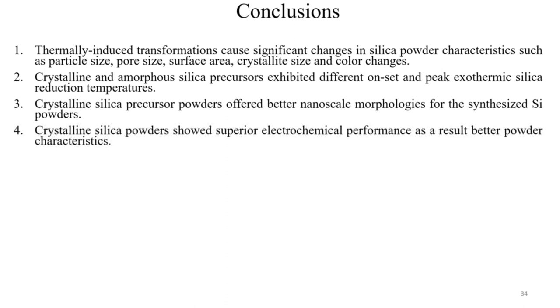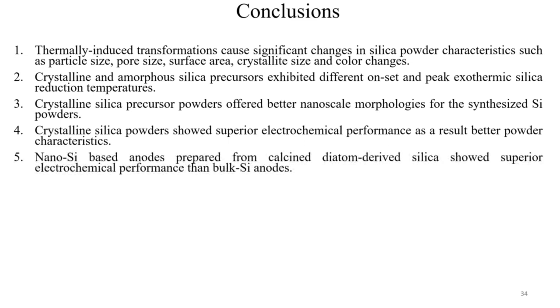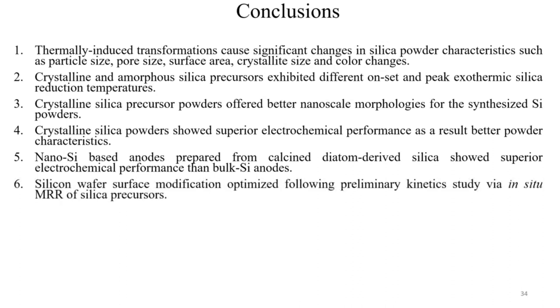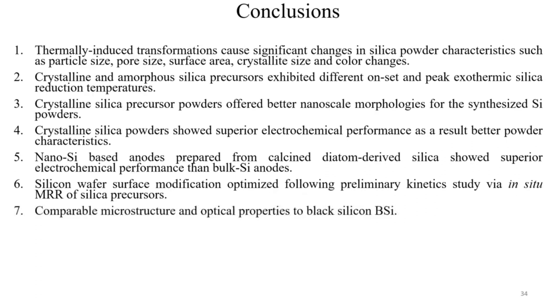and the crystalline powders showed superior electrochemical performance as a result of better powder characteristics, and the nano-sized silicon anodes prepared from calcined diatom derived silica showed superior electrochemical performance than bulk silicon, and the silicon wafer surface modification was optimized following preliminary kinetic study via in situ magnesiothermic reduction of silica precursors, plus these surfaces had comparable microstructure and optical properties to black silicon.